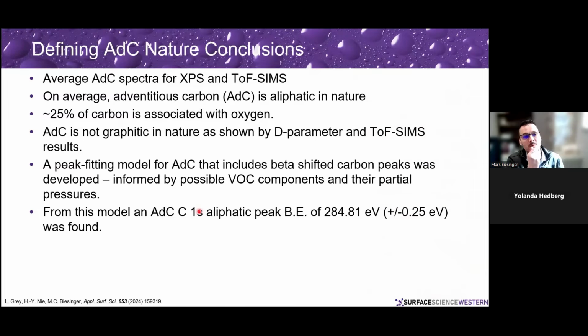So some conclusions from that: we found that, on average, adventitious carbon is aliphatic in nature with about 25% of carbon associated with oxygen. It is not graphitic in nature. We did some D-parameter work and ToF-SIMS work that showed that. And if we use a peak fitting model for ADC that includes the beta shift peaks, we can remove some of the error in that peak positioning. We found an aliphatic peak binding energy of 284.8.